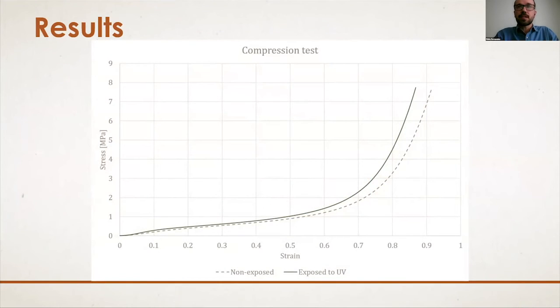Now in terms of mechanical testing regarding the compression tests, from this point on average results are presented, but good repeatability was achieved. In these tests, we can see that the samples exposed to UV exhibited higher stress levels. Although the difference is almost insignificant for small strains, this difference increases with the strain, being maximum at the densification stage. So the UV exposed samples presented always higher stress plateaus as well as sooner densification. It is possible to observe that samples exposed to UV showed a higher compressive strength, and reached densification for strains 5% lower than the ones necessary to cause densification in the non-exposed specimens.